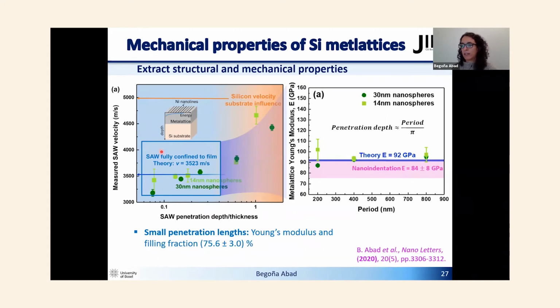From there, we can extract the Young's modulus and also the filling fraction. This is the percentage of silica that we really have in our metalattices. And we did that, and we extracted different values of Young's modulus for these three different gratings. We saw that they are in very good agreement with theory, which is based on continuum mechanics, and also with another independent technique. In this case, we did nanoindentation. So that's from the fully confined waves.